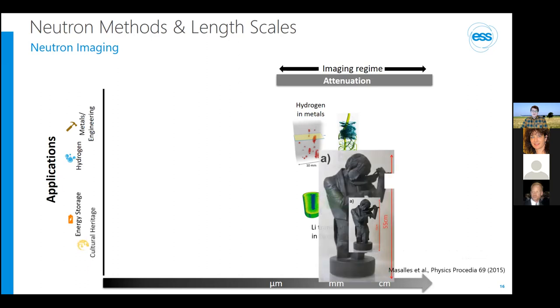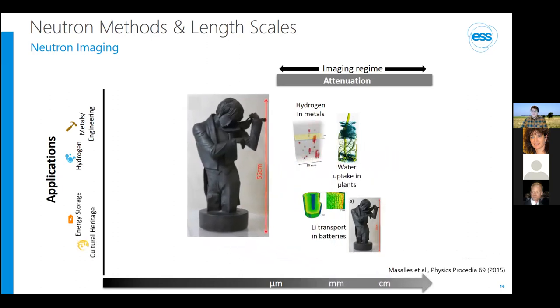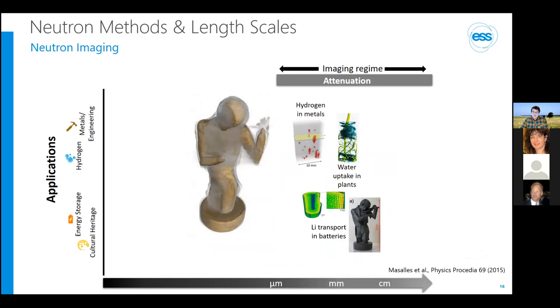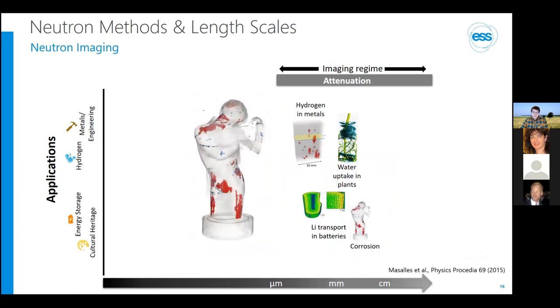And due to its non-destructive nature, neutron imaging has been extremely successful for cultural heritage applications. You can see, for example, a lead statue. And since the lead can be easily penetrated by the neutrons, one can reveal the inner wooden kernel and, moreover, even locate regions that have been soldered or corroded inside of the statue.